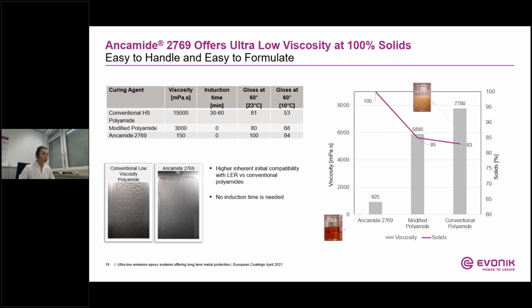Conventional low viscosity polyamide exhibit poor compatibility with liquid epoxy resin and require an induction time before application. These products are usually slow to dry and give rise to tack and poor quality films, often unsuitable for applications at lower temperatures.